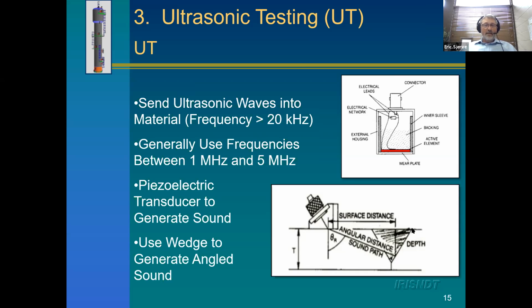With ultrasonic testing, what we're doing is sending high frequency sound waves into a material, and we're generating those sound waves with a piezoelectric crystal. And then we're using Snell's law. Snell's law is just refraction. So if we want to generate an angled sound beam, we just put a wedge on it like that bottom picture, and we get an angled sound beam in the material. And the angle is based on Snell's law, which is kind of what you see in Pink Floyd's prism. You just get different refraction based on different angles.